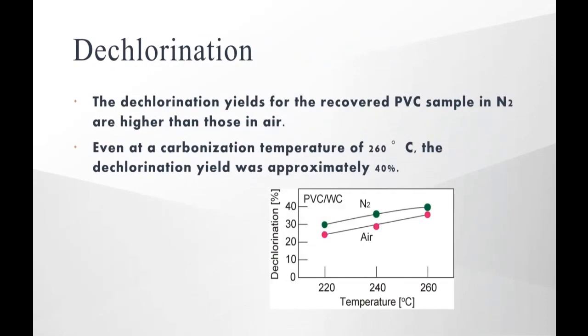This is a result of dechlorination of PVC. The dechlorination yield for the recovered PVC sample in nitrogen is higher than those in air. Even at the carbonization temperature of 260 degrees C, the dechlorination yield was approximately 40%.